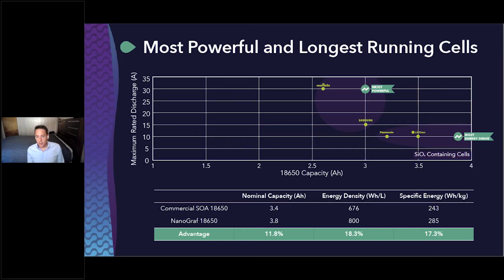Again, there's a lot of data here, but this is just a demonstration of what we've been able to do with our material in a standard 18650 cell. As we say, we believe we've made what still is the most powerful 18650 cell with our technology. That was a cell that was about a 3 amp hour capacity that could safely discharge at 30 amps. And that was a cell that was really geared towards power tool makers. Looking at some of the other tier 1 competitors, we're able to achieve that incredible capacity and discharge rate through the combination of the core and surface technologies that we use.